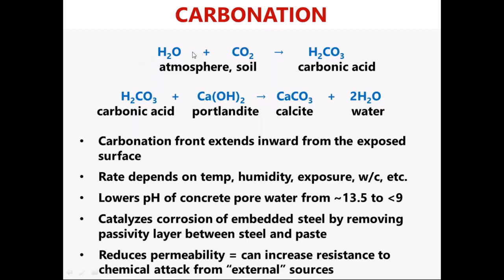So concrete that's even indoors will carbonate, not just exterior concrete. But the carbonic acid, once it's formed, interacts with the portlandite, the calcium hydroxide in the paste, to form calcite and water. So here we're forming calcite again. We're forming calcite in the paste. We're turning the portlandite into calcite. That's the carbonation we're talking about.